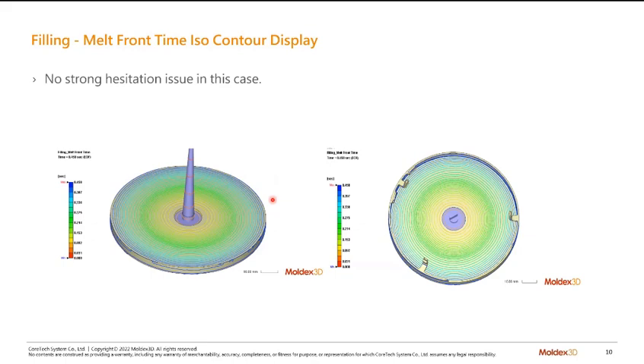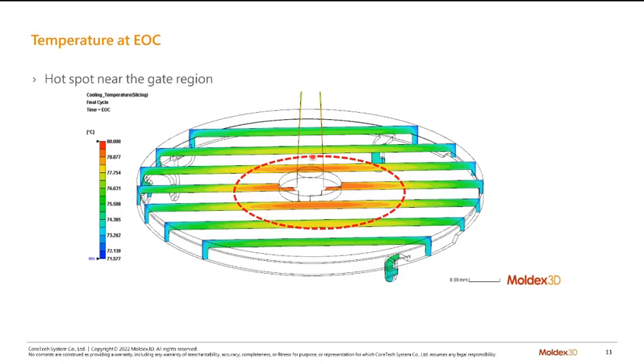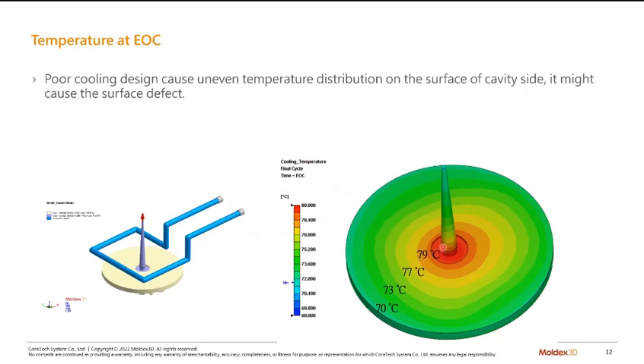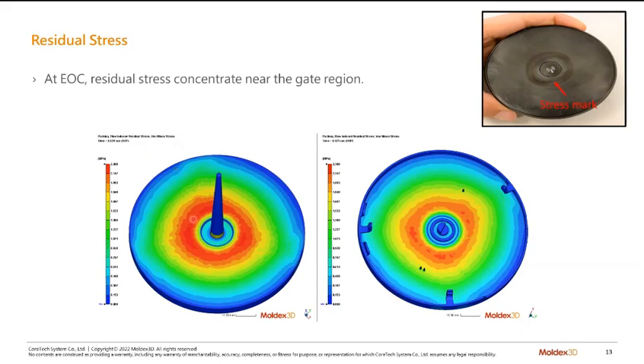And then they check the temperature in this cavity, and they find out that there's a hot spot near the gate regions, and the temperature difference is around 9 degrees from the center of the part to the outer of the part. And then they check the residual stress. They can see that there's a high residual stress on the bottom and the top of the cavities, and it matched the problem in reality. And they think this one is the stress mark, and it's caused by the poor temperature distribution inside the cavities.